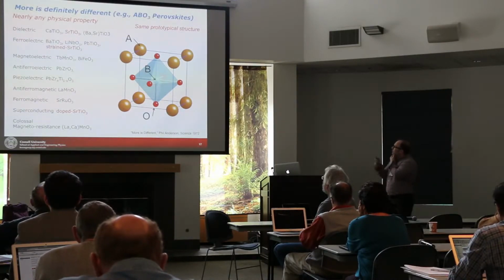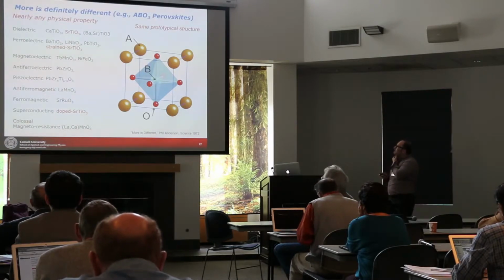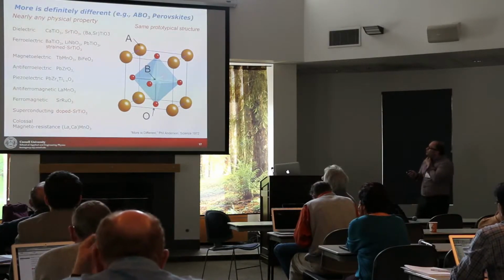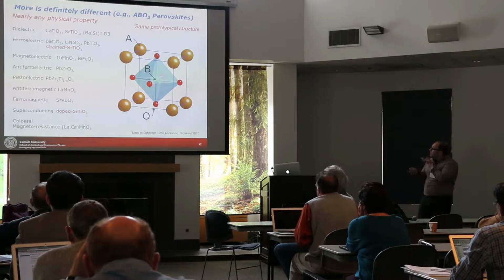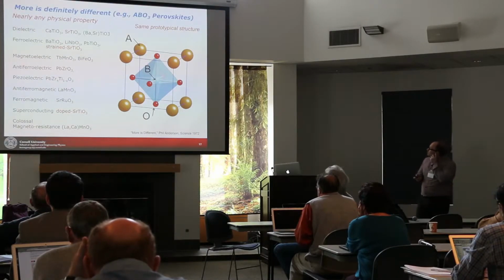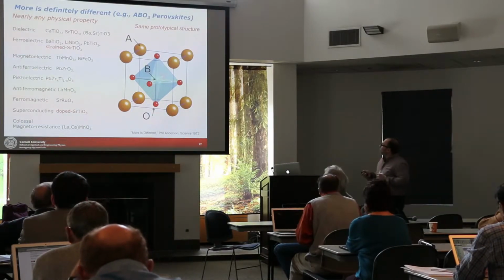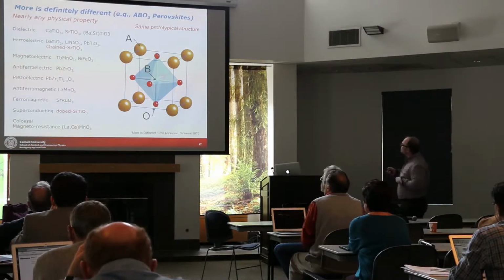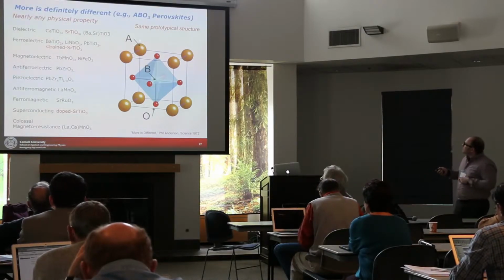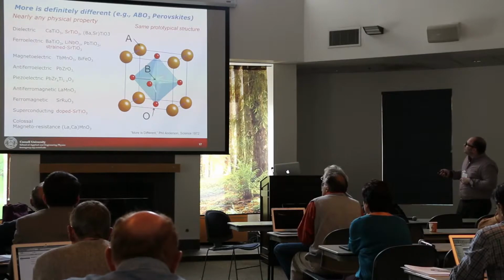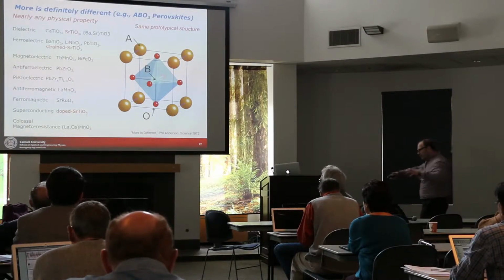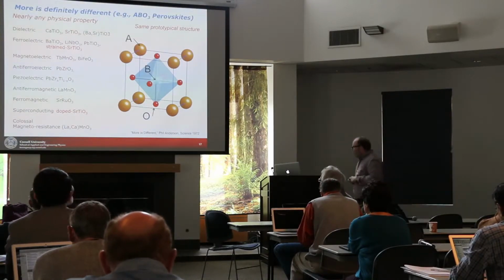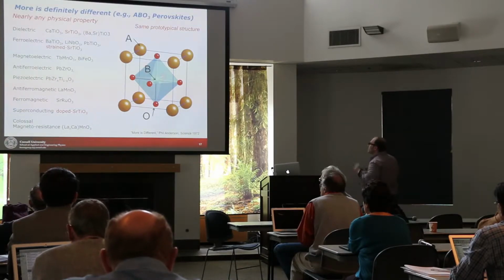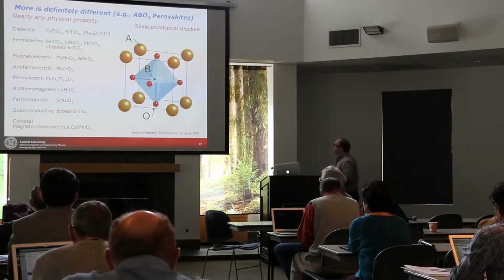The perovskites, which I mentioned on the previous slide. It's simple in the sense that the prototypical structure seen here is relatively simple. It's a cube. Can't get much simpler than a cube on a lattice. There's only 5 atoms in this prototypical structure. It's an ABO3 compound. A sits in the corner of the cube. B sits in the center of this oxygen octahedra. The octahedra are corner shared, and there's a 3-dimensional network of these octahedra.